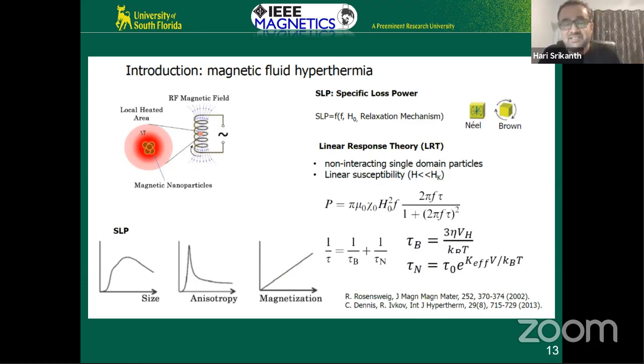Well, that's easier said than done, because if you make nanoparticles, as soon as your particle size goes down, the magnetization drops like a rock. And this is because the surface is disordered. The surface spins are disordered, so the ordered magnetic phase volume goes down. And so essentially it's very difficult to make magnetic nanoparticles that have the same magnetization as the bulk moment, for example.